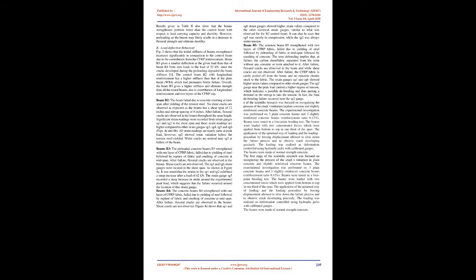The control beam B2 with longitudinal reinforcement has a higher stiffness than the plain beam B1, which had premature brittle failure. Overall, beam B5 gives a higher stiffness and ultimate strength than all the tested beams, due to the contribution of longitudinal reinforcement and 2 layers of the CFRP strip.